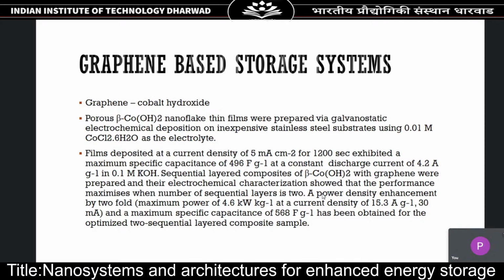So what we have done is we have sequentially deposited the composites of beta cobalt hydroxide with graphene, and we have found that the performance maximizes when the number of sequential layers is 2. I will show you some subsequent graphs which actually show the behavior. And we have also got a power density of 4.6 kilowatt per kg. And we also got a specific capacitance of 568 farad per gram for the 2 sequential layered composite samples.